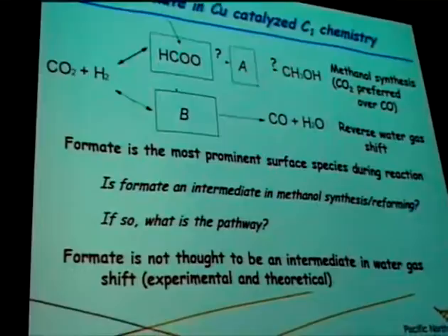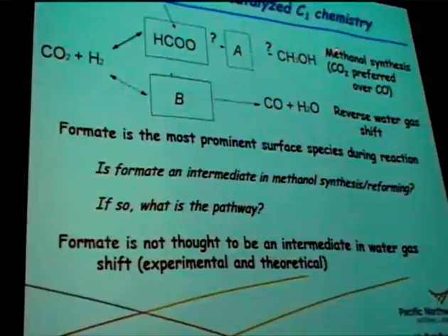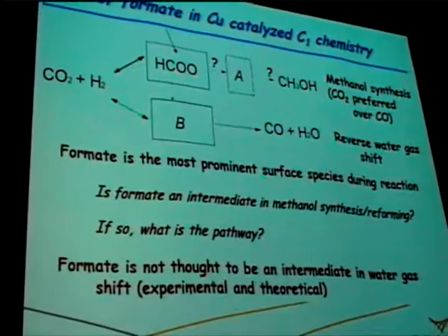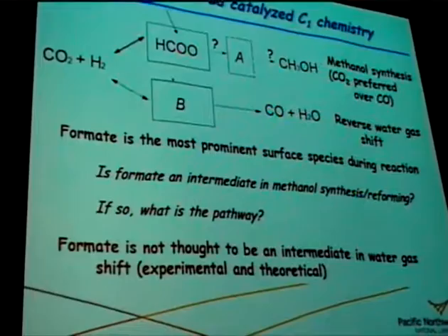But the question remains whether it's got a role in methanol synthesis. Of course, it's sitting there on the surface, as it does for water gas shift. If you look in IR, it's the most prominent surface species during the reaction, and some of the coverages you saw yesterday in the plenaries combined that.